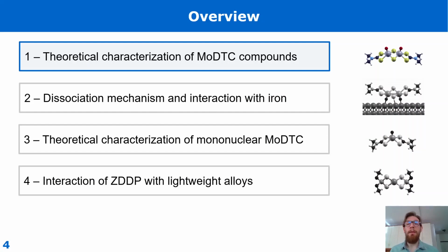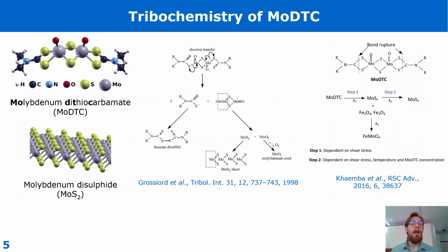Now I'm going to describe the theoretical characterization we have carried out for MoDTC compounds. MoDTC compounds, molybdenum dithiocarbamates, are a group of different chemical structures, like the one represented here, that are very important in tribology because they are known to reduce the friction of steel by around 1 order of magnitude. The mechanism behind the lubrication of MoDTC relies on the fact that MoDTC breaks down and forms molybdenum disulfide tribofilms. In our simulation here we consider small chains in the lateral groups of MoDTC to reduce the